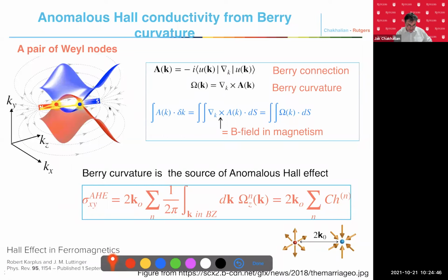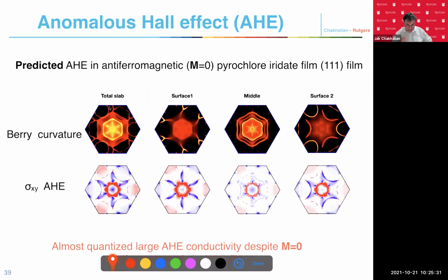This is the conductivity in the x and y direction, so it's a transverse conductivity. It is really the distance between two Weyl nodes in momentum space multiplied by the Chern number, or the chirality of these things. So it means that if you measure the conductivity, the anomalous Hall effect, in this crystal, then you should see a strong anomalous Hall effect, even though the magnetization is equal to 0. Okay, in this material.